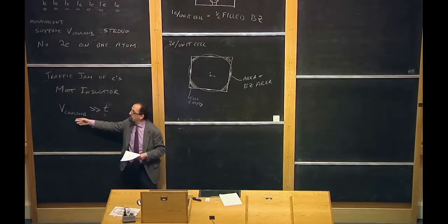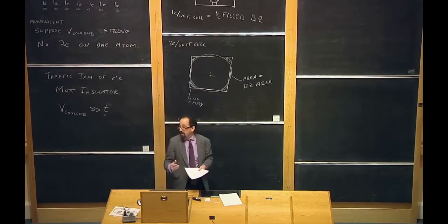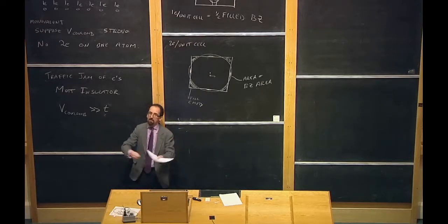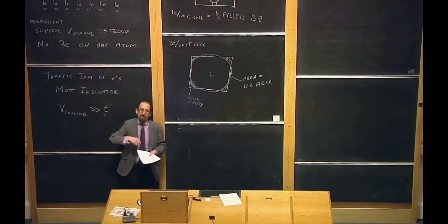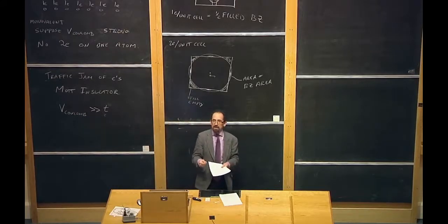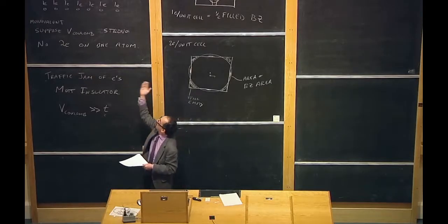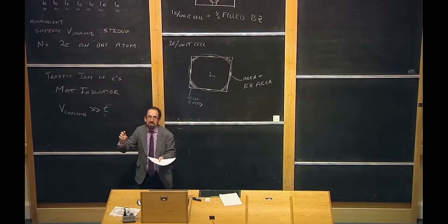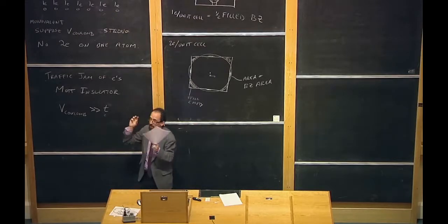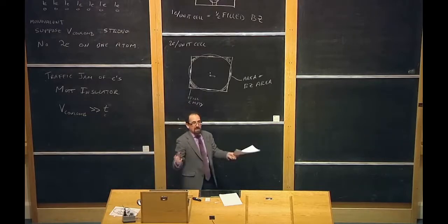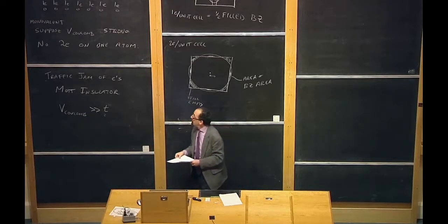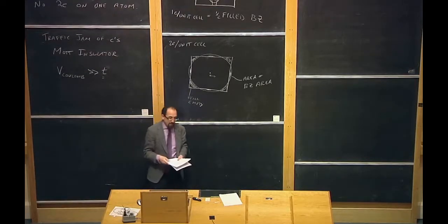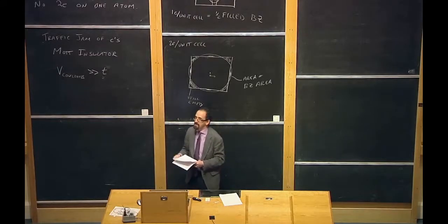If it's allowed to spread out its wave function. But if the Coulomb interaction is much, much stronger than the hopping, then the electron would gladly sacrifice the amount of kinetic energy it's gaining by forming a plane wave in order to prevent itself from ever sitting on a site where there's already another electron. In which case, it will set up one of these. It's a very classical picture of just 1 electron sitting on each site, and no quantum mechanics has to be considered at all. It's an insulator because no one can move, because no one wants to sit on the neighboring site because there's already an electron there. So this effect is completely left out of band theory, and so it's kind of a failure of band theory, and at the very end of the course, we'll come back and analyze this again.